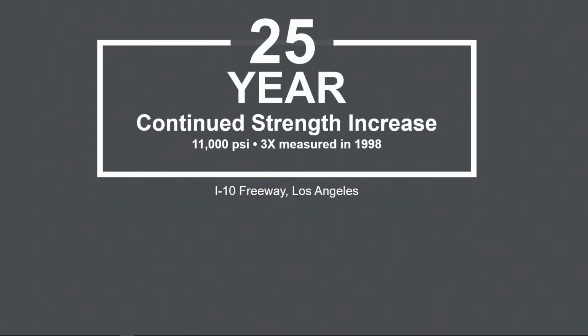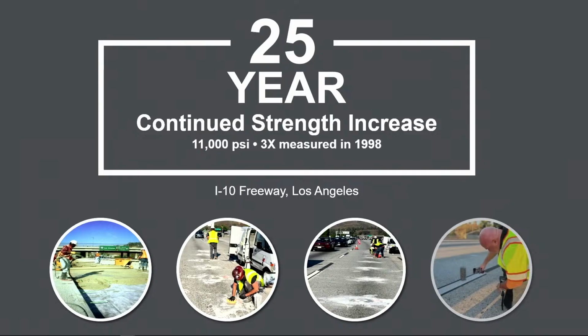So speaking of durability, back in 1998, Caltrans installed 2 lane miles on the I-10 freeway in Los Angeles using Rapid Set cement concrete. Well, fast forward 25 years later, and we went out and we were able to sample that in-place concrete. And what we found is that concrete, after 25 years in the freeway, had a compressive strength of over 11,000 PSI and a calculated flexural strength of almost 3 times what it was at opening back in '98. So that concrete will be in service, I think, for the next 25 years.